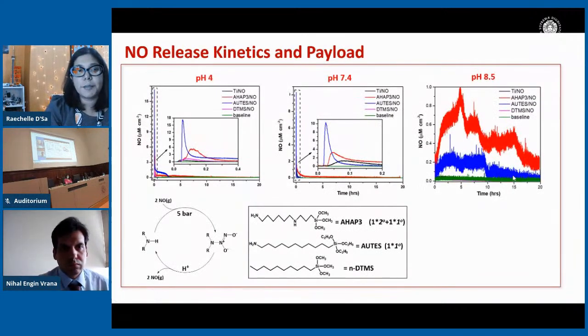We then looked at the NO release profiles using chemiluminescence that quantified NO as it was released off the surfaces, and because it is controlled by pH, we observed what happened at pH 4, at pH 7.4, and at pH 8.5. At pH 4, the nitric oxide should release the fastest, and the lower the pKa of the amino group, it should be an easier release from the surface. So for our three different silanes, what we can see is that the AUTES silane, with just the terminal amino group, has a burst release of the nitric oxide. The AHAP, which has two different positions for the nitric oxide, releases it with a much slower release profile.